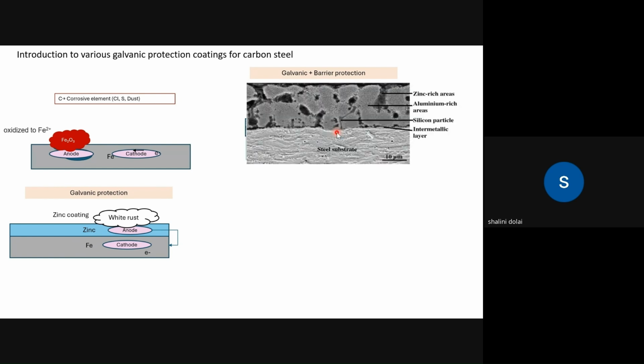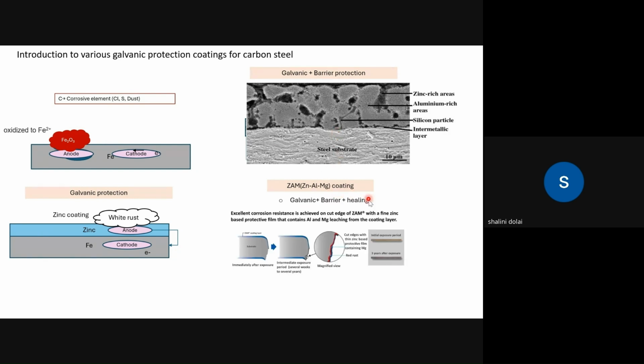Now the third approach was to go for zinc aluminum magnesium coating, which is flexible like zinc coating but has double electron protection from zinc, aluminum and magnesium. And the magnesium ions can migrate in my system, and wherever there is a cutting, they can travel to that part and offer corrosion protection, which is called healing.